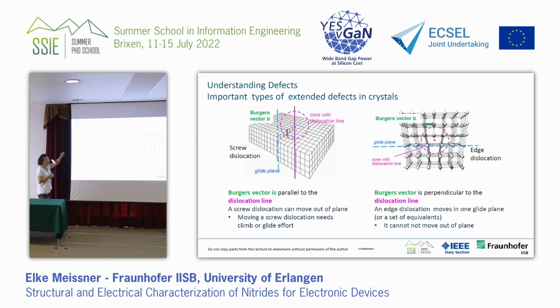Understanding the defects, so a screw dislocation. Finally, we want to come to the point: why do dislocations act differently? You have, for example, screw dislocations and you have edge dislocations. They are atomically and energetically different in character. If you have a screw dislocation, it means a lattice point goes around the lattice plane like this, inside the lattice. Whereas if you have an edge dislocation, you have your lattice, and imagine you put an extra layer in the middle of this, which is depicted here.